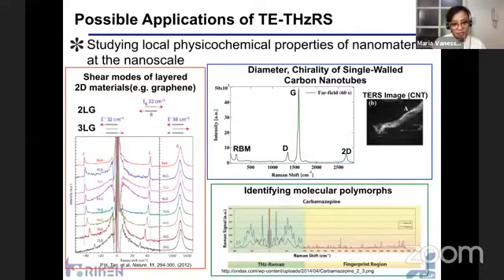So the advantages of using tip-enhanced terahertz Raman spectroscopy, and also the terahertz or low frequency Raman that you can detect, are, for 2D nanomaterials, which are layered, they're very useful to find out the number of layers of your sample, for example, graphene or molybdenum disulfide. And then another interesting aspect is that using these low frequency Raman modes for carbon nanotubes, you can determine the diameter and also the chirality based on what we call the radial breathing mode.